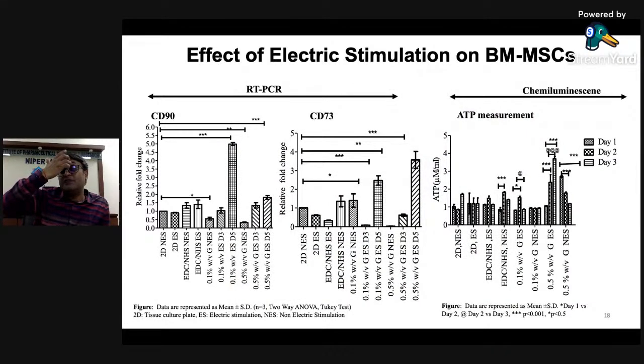After giving electric current, we wanted to see what happened to the stem cells, whether the stemness was retained or not. Looking at two markers, CD90 and CD73, we found that the electric stimulus actually promoted the stemness in 0.5% graphene, showing large deviations, much promoted. So stemness is maintained or increased when electric current was given in the 0.5% graphene incorporated collagen cryogel.